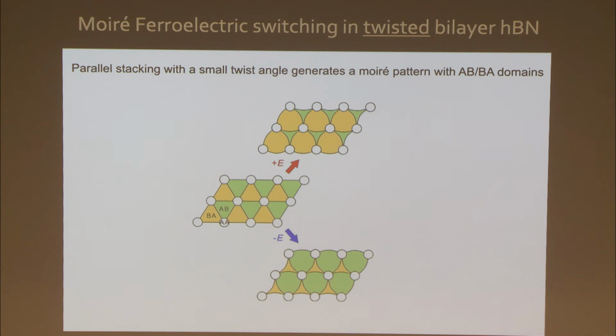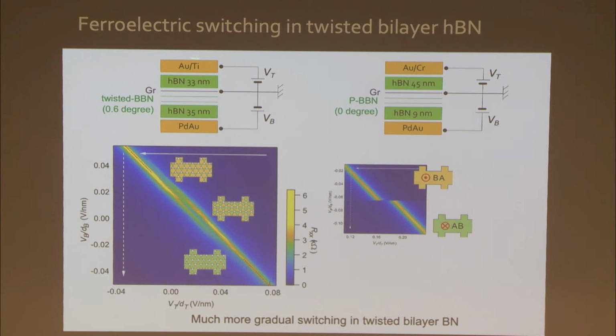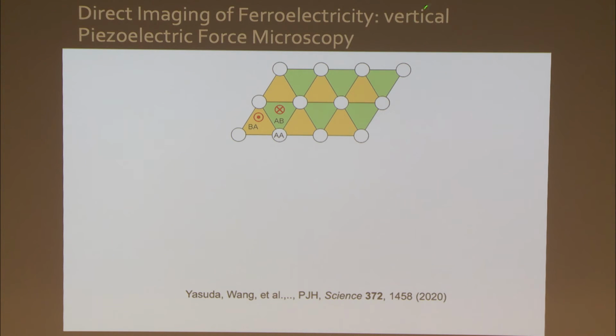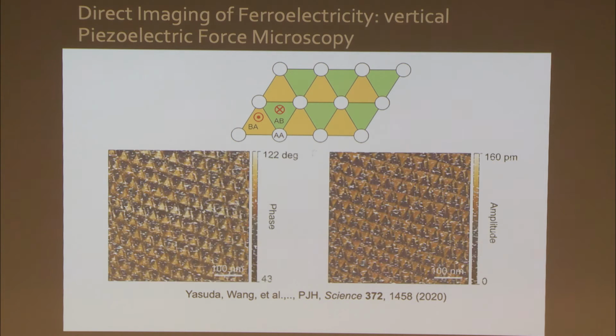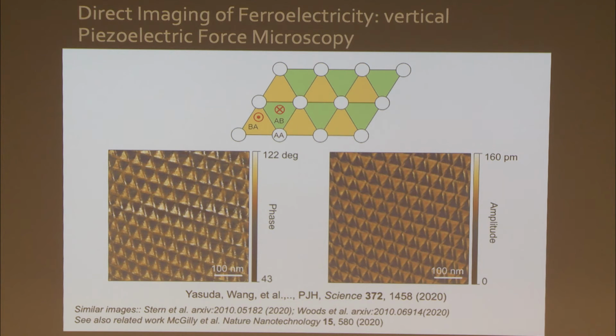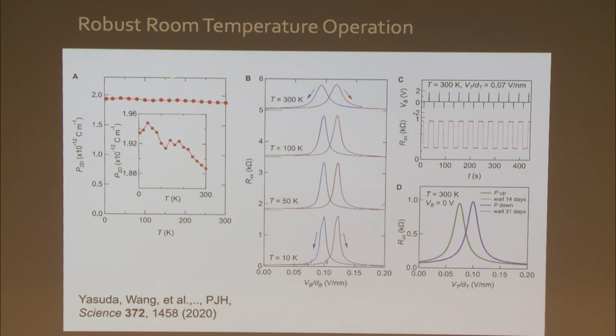Okay? And indeed, if we fabricate devices where we have a small angle, like 0.6 degrees in this case, we can see that we change from one type of resistive state to the other, but gradually, rather than abruptly. Okay? Can we actually visualize these moire antiferroelectric domain patterns? We can. And we can use a technique called vertical piezoelectric force microscopy. And using this technique, we can directly image the up and down electric field domains in the structures. You can just put them on top of each other, and you can see nicely that it aligns with our moire lattice.